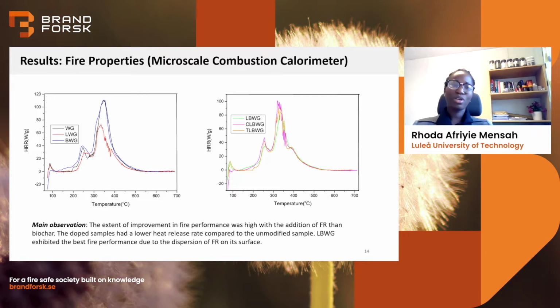So if we look at the undoped samples, we see that the peak heat release rate, which is the maximum heat release rate that is recorded, for the neat wheat gluten and the biochar wheat gluten are very similar. However, the addition of Lanasol to the wheat gluten improved the fire performance of the wheat gluten. And this is because biochar is a reinforcement and Lanasol is a fire retardant. So Lanasol protects the materials from the heat.